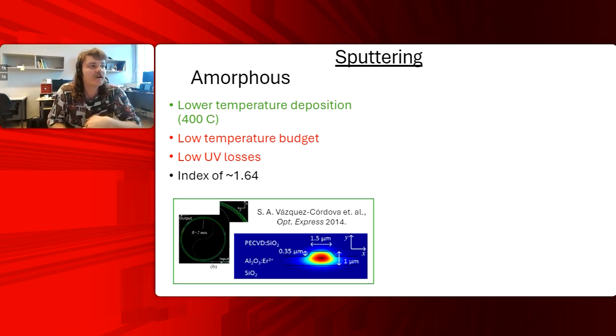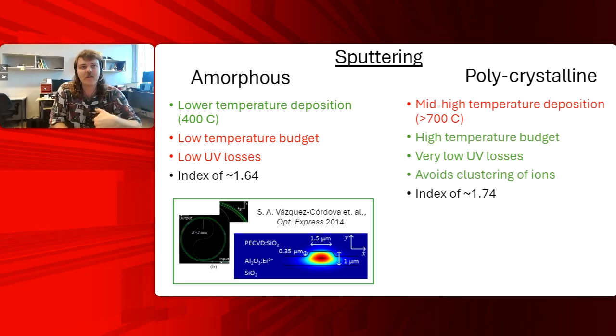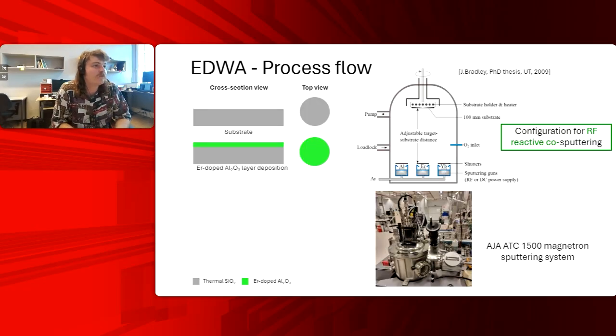However, when you sputter at a slightly higher temperature in aluminum oxide, you get a polycrystalline phase, which does require a higher temperature. Maybe that's seen as a drawback because you can't do back end of line deposition of this material anymore. However, this polycrystalline aluminum oxide has a very high thermal budget, has very low UV losses, and can avoid clustering of these rare earth ions, which, as I mentioned, is a nasty business for erbium amplifiers. We do so by doing reactive sputtering.